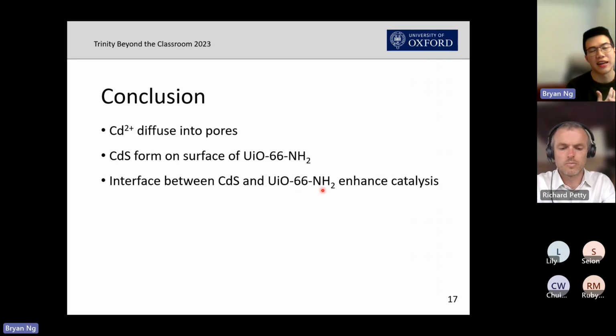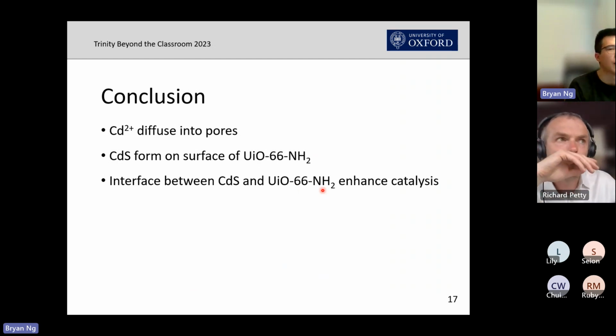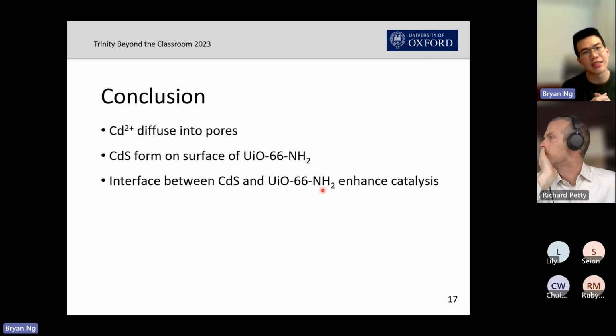enhancing the catalysis. We did some other characterization techniques such as X-ray absorption spectroscopy, which tells you the coordination environment of cadmium inside. And then we also analyzed the particle size of the cadmium sulfide from the microscopy images that I previously showed in order to reach these conclusions. So these are the sorts of things that we do. We do some synthesis, we do some catalysis, and then we do some characterization, and then tell the story of what exactly is happening in these systems.